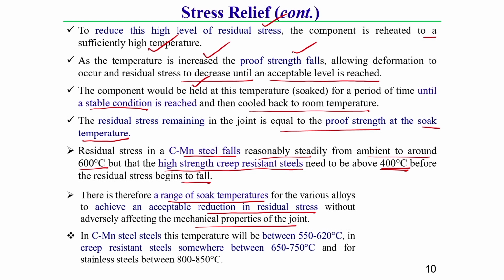That is why here I have written what should be the temperature range for stress relief operation. In case of carbon manganese steel, this temperature will be between 550 to 620 degree centigrade. In case of creep resistant steel, somewhere between 650 to 750 degree centigrade, and for stainless steel between 800 to 850 degree centigrade. So, here I have just discussed in detail about stress relief post weld heat treatment. I have also discussed a term called proof strength. Generally once the temperature increases, the proof strength falls.